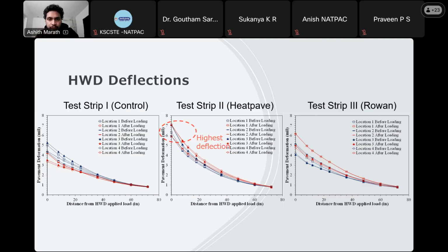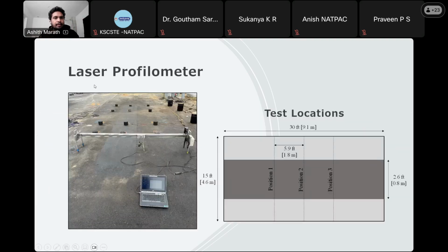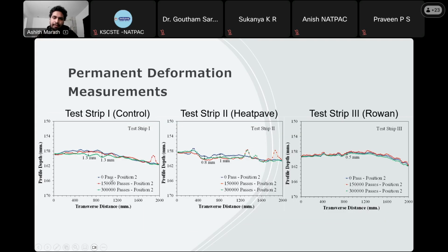Yeah, and the laser profilometer was done at three different positions, and the results were that all three pavement test strips had almost negligible rutting. If you look specifically at the values, you could see a minor increase in the permanent deformation in test strip 1, which is the control section, and the ECA pavements were having negligible permanent deformation.